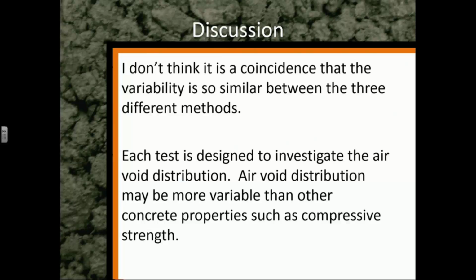Each test is designed to investigate the air void quality of the concrete, at least as long as you have good aggregates and you have a good water to cement ratio. And air void distribution, air void quality, air void spacing, air void size may be more variable than other properties that we're used to dealing with, such as compressive strength. Compressive strength has about a coefficient of variation of around 10%. This one's got a higher one, but it may be that this parameter in concrete is just a little bit more variable. So you have to be a little bit careful about how you use it, but that's okay. I'll talk about that coming up.